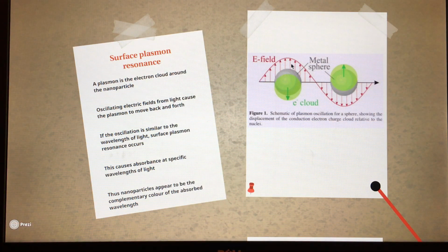Depending on how long the electrons take to slosh back and forth in the particle, it can be in resonance with the oscillations of light that is hitting this nanoparticle. And when that happens, we get a surface plasmon resonance. This causes a strong absorbance at the specific wavelengths of light where the electrons of the nanoparticle are forced into oscillation due to this strong coupling between the electron cloud and the wavelength of light shining on it. This absorption results in the bright colors we see in our nanoparticle solutions.